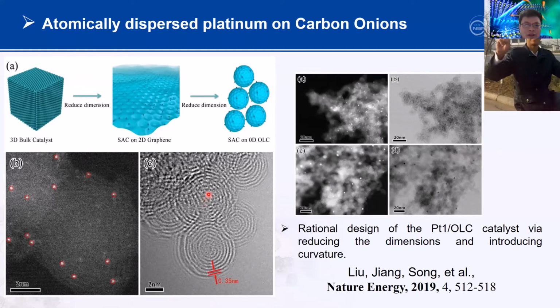So here we selected the carbon onion as a support, and then we use ALD to deposit some particles, and we try to decrease the particle into the atom. So this is almost a single atom in here. You can see which is located, which is supported by the carbon onion. This is too tiny, so we need a technique to identify the structure.